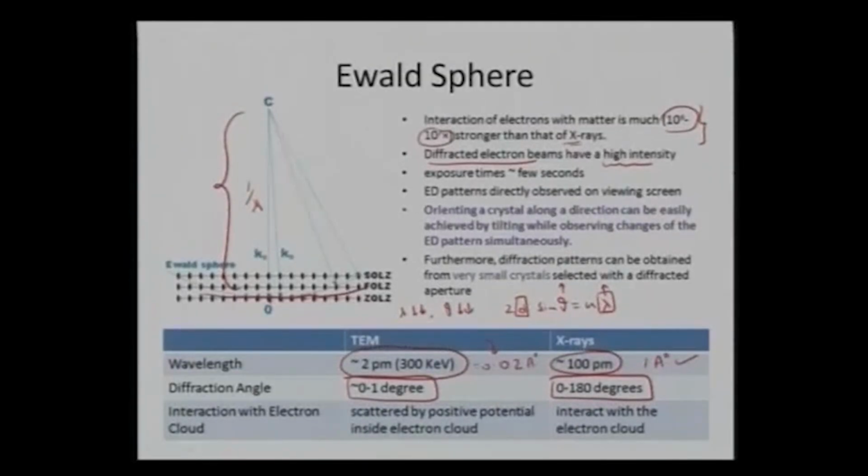So, what I have to do, my exposure time automatically reduces to only a few seconds, whereas for taking an XRD spectrum, I spend 40 minutes, 45 minutes, an hour or much more than that to collect the overall spectrum of how my diffraction has really occurred. And also I limit it to a certain range, maybe say 0 to 180 degrees or 20 to 90 degrees. So, I have to limit my diffraction angle to a theta value, and still it takes me a couple of hours,